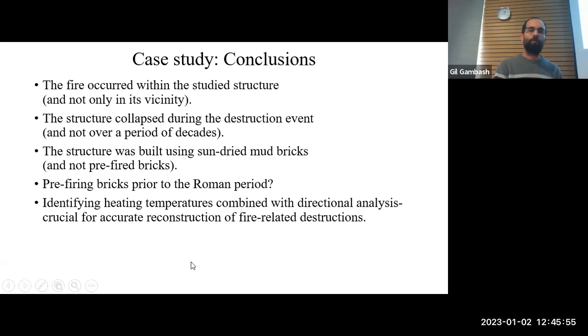Now, pre-firing bricks prior to the Roman period was suggested in the Namda paper and in several other papers recently. And I personally think that it still needs to be reevaluated, because I'd be convinced that a wall was built of pre-fired bricks if we sampled the different bricks and every brick gave us a completely different direction. One would point that way and one that way, not north and not down. But if all the bricks give us more or less the same direction, it doesn't seem likely that they were pre-fired. We showed it here.